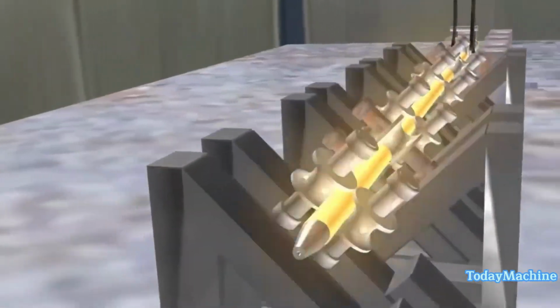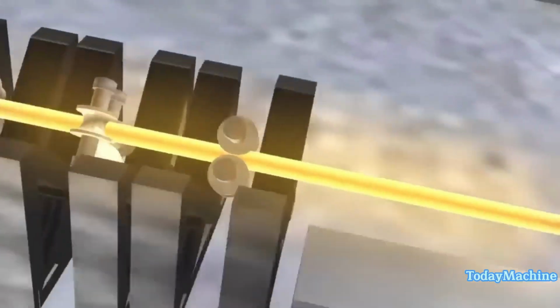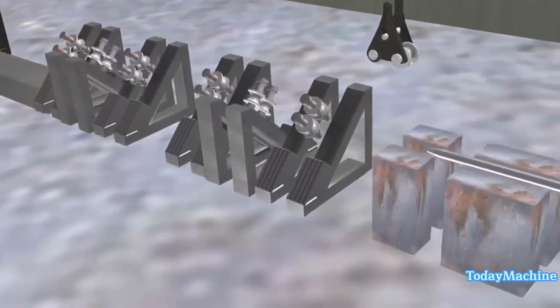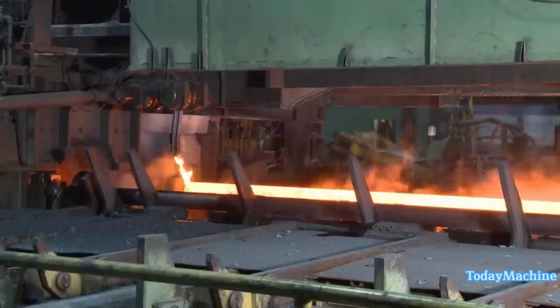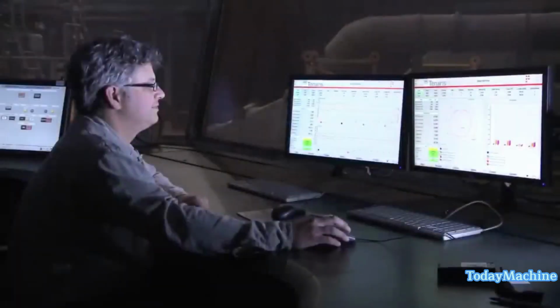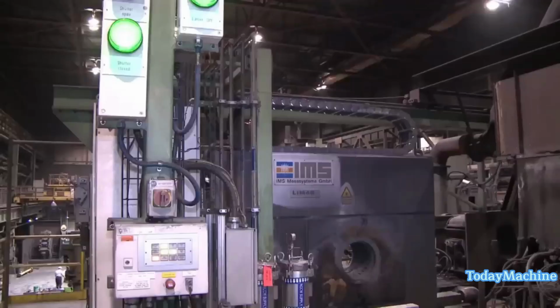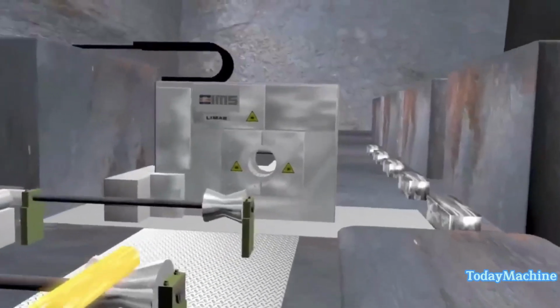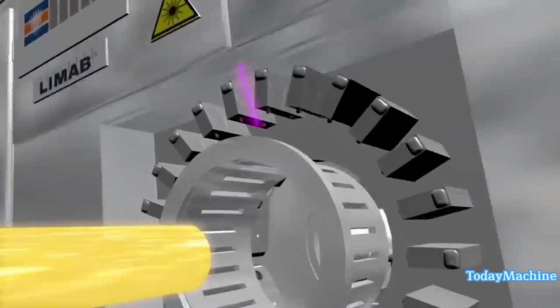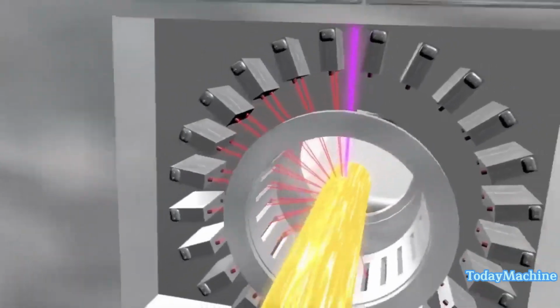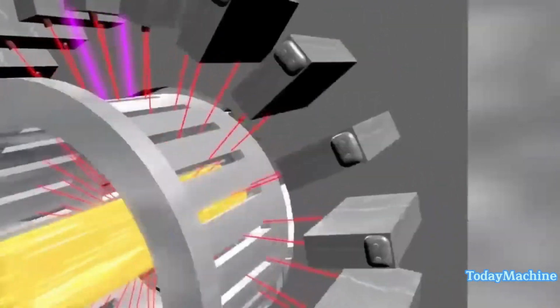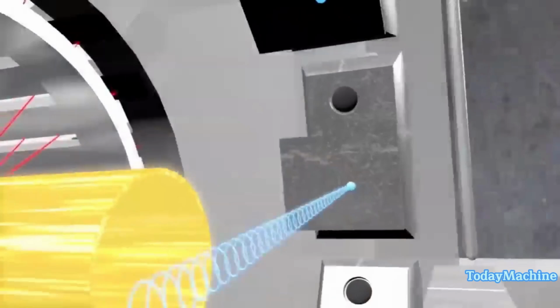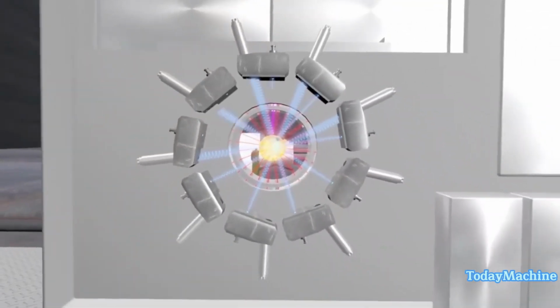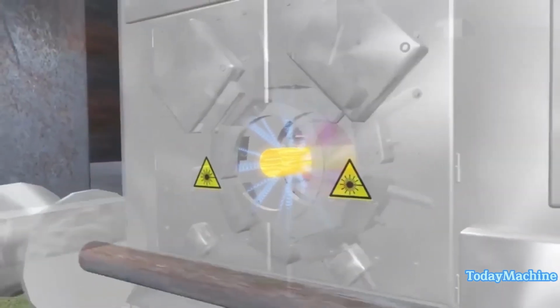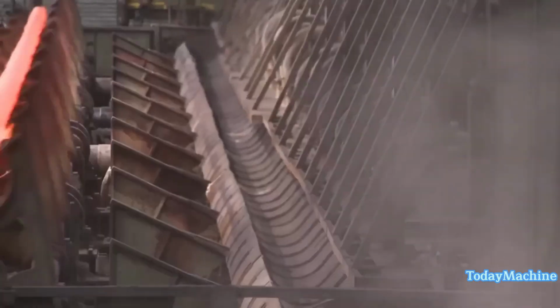The hollow shell formed at the piercer has a wall thickness that is further reduced to the final tolerance by longitudinal rolling on the retained mandrel mill. The outside diameter is rolled down by a series of 7 reduction stands using a chrome-plated tool steel mandrel. This reduction in diameter converts the heavy wall thickness of the piercer hollow into length as it passes through the mill. After passing through the mill, a mill extractor decreases the tube's outside diameter further as it extracts the tube while the mandrel is withdrawn.